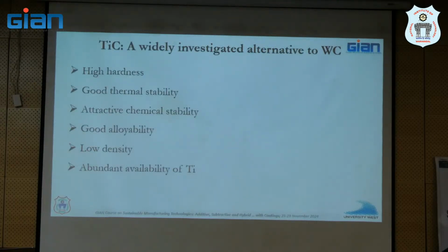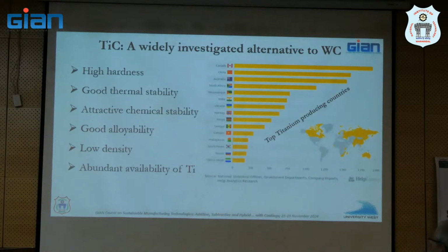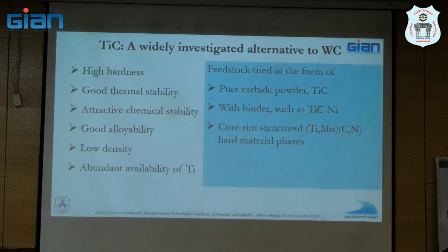Correct? So we've been looking at, for instance, titanium carbide as an alternative. It has all the good attributes that you would want in a wear-resistant coating. The challenge is, how do you retain TiC as TiC? You start with TiC, but after you spray, how do you get TiC in the coating, right? But we've been looking at different ways. Why is TiC exciting? Because it has no problems that tungsten has in terms of availability worldwide. Yeah, a lot of titanium available everywhere, including in India. India is a pretty large producer of titanium, actually, right?